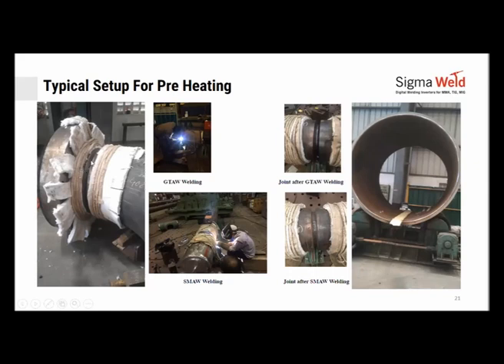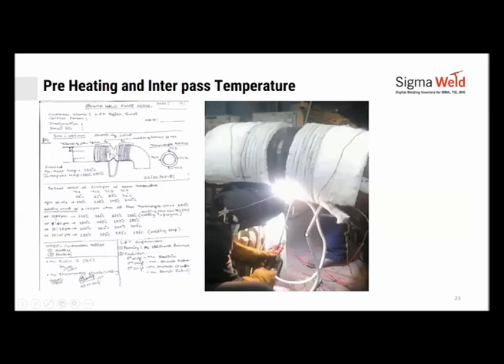If you were to do this with gas or with an electrical pad, the time required to wind this on an electrical pad itself would be close to 2.5 hours, because you can imagine the kind of curves that are there. Whereas this in induction would take you about 10 to 15 minutes to set up. Just put the insulation, wind the coil like you wind a rope, fit it, and you could start. The root runs or TIG welding being done, subsequent runs of SMAW or arc welding being done, the coil is in place and not a problem. You could keep welding while the coil is there, maintaining or monitoring your interpass temperatures.